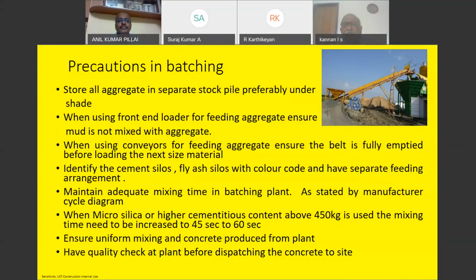Have a quick quality check at the plant before dispatching the concrete to site. Normally, after mixing concrete, in an RMC plant 15 to 20 minutes is taken for preparation of the DC, preparation of the sample, everything. The DC and all can be made once the truck is placed, because you know to whom you are delivering. Even if you are able to reduce the delay by 5 or 10 minutes, the truck can reach 10 minutes earlier, before the concrete starts hardening, and the concrete can go in place. So you should plan to streamline things so that after loading, within a very short period of 5 minutes or even less, the truck moves out from the plant. Then only the actual concrete as produced can be delivered to the site.